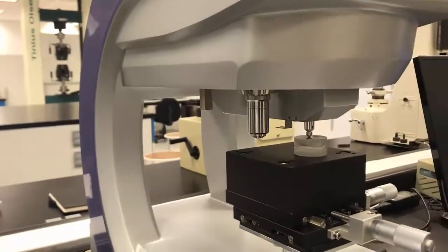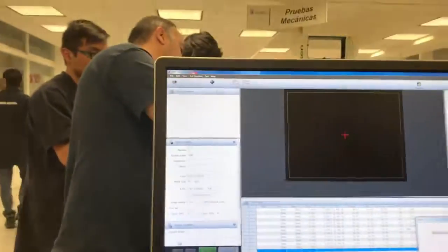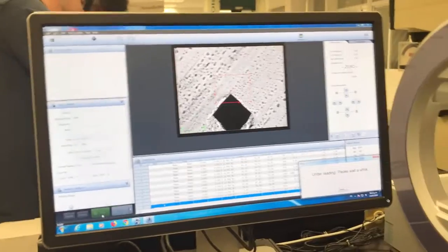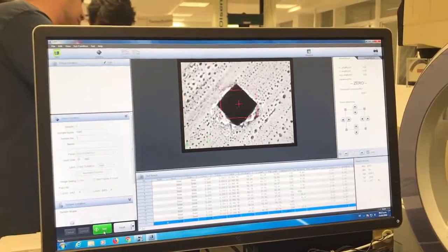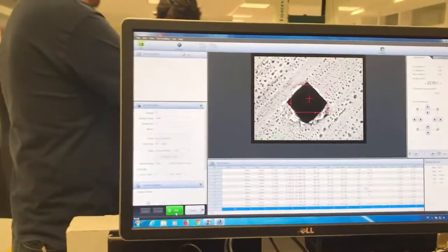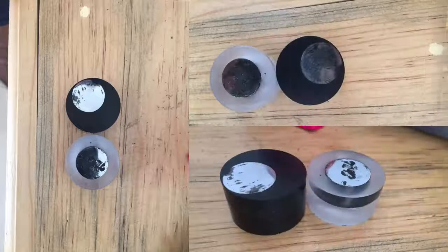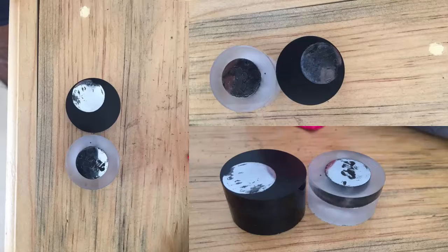For these samples, we only used the digital version of the Vickers test. After analyzing the results, comparing them to the ones obtained with the non-treated samples, we concluded that quenching increased the hardness of the steel, as can be seen in the results. In metallurgy, quenching is used in steel by introducing martensite, making its crystal structure transform into a much harder one. This gives the steel characteristics such as resistance to deformation, making it very efficient.